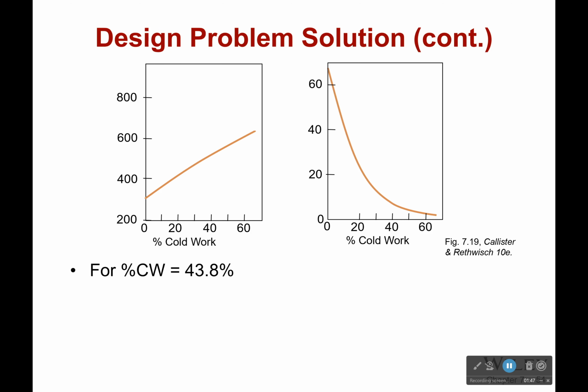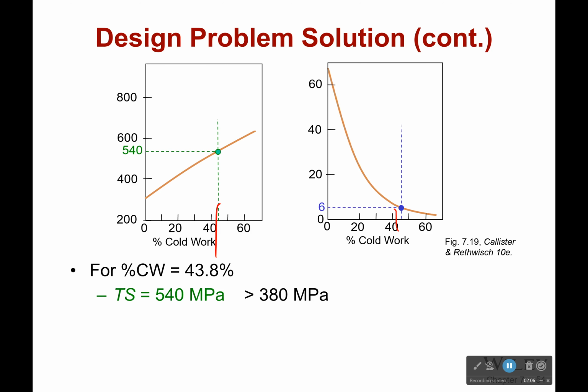So now we'll need to look at some tables. We've got 43.8% cold work, so I go over here and trace it up to the line. And I see that at this point, my tensile strength is 540 megapascals, which is way more than the 380 I needed. However, my percent elongation is 6%, which is way less than I need. I need at least 15.